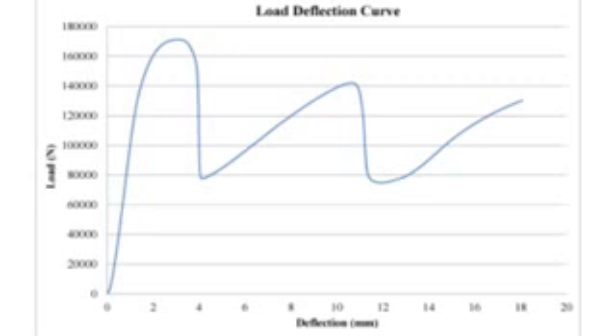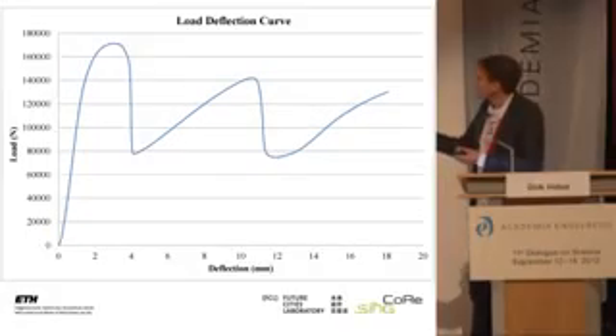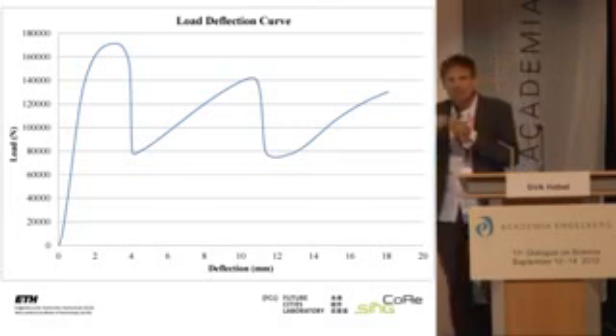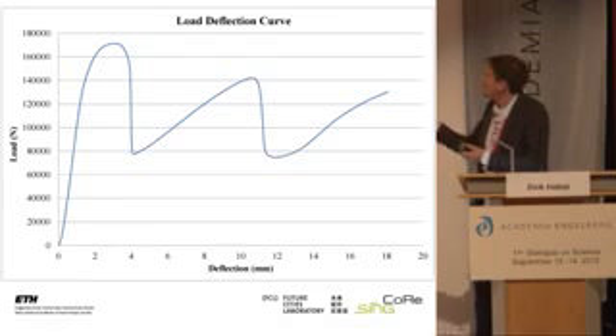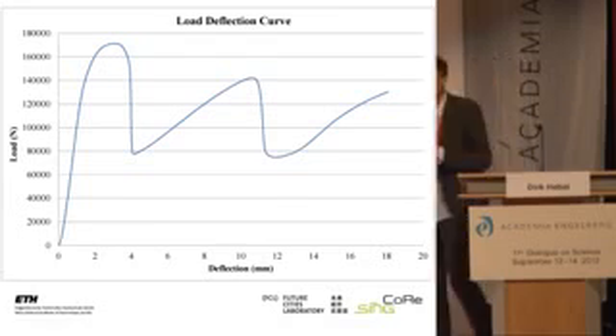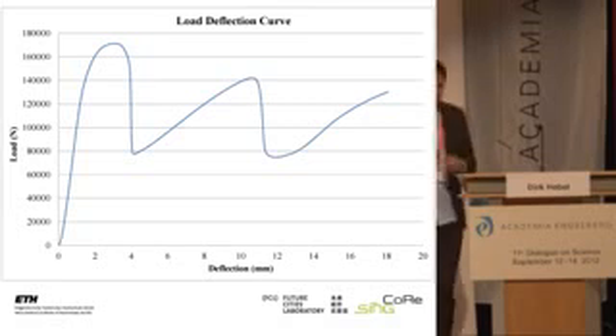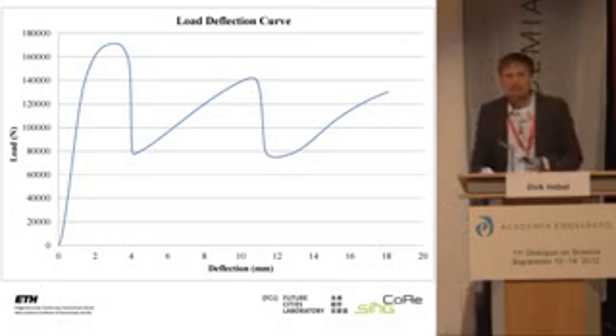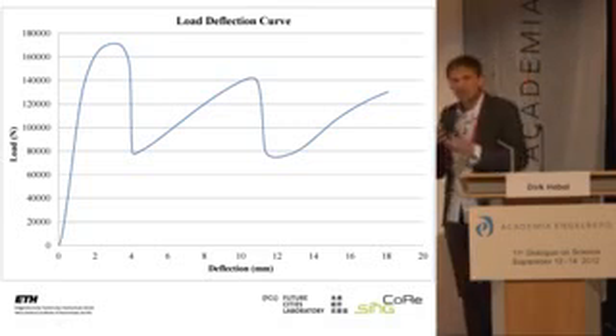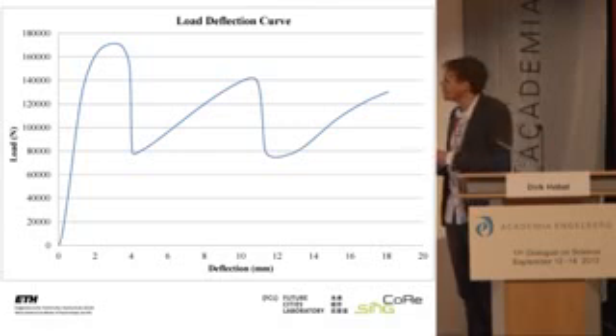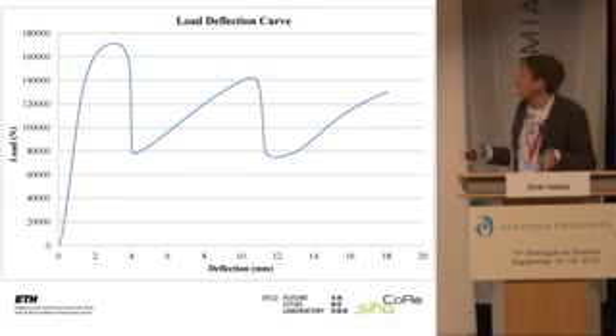And we get very interesting results out of compression. You see here that the curve is going up. So that means compression is fine. And then we get to a point where certain fiber bundles fail, but the material recovers. So when you start to press again, the material has the capacity, because other fibers are taking over the action. We have very interesting curves showing that bamboo is such a flexible material, and you know it also from these images from construction sites where it's used as scaffolding, that bamboo is such a kind of living material that these ones would help us a lot in terms also of earthquake resistance in these composite materials.